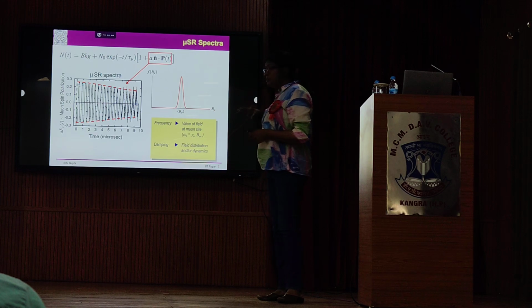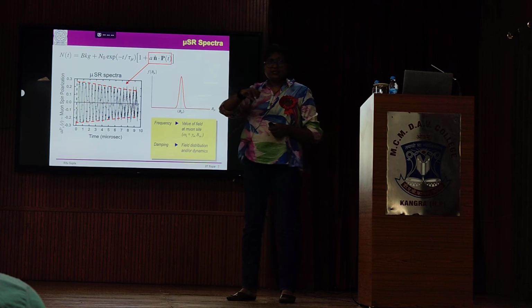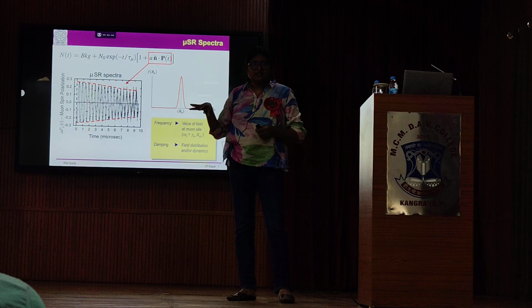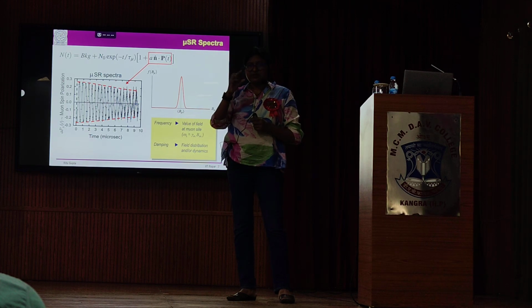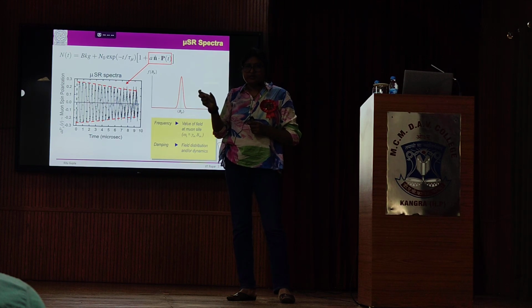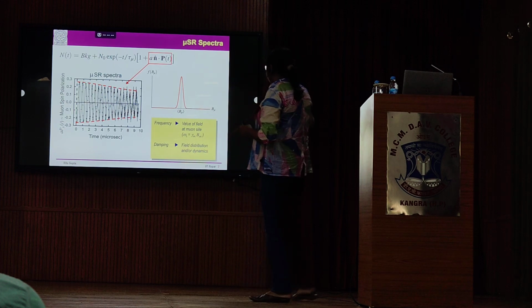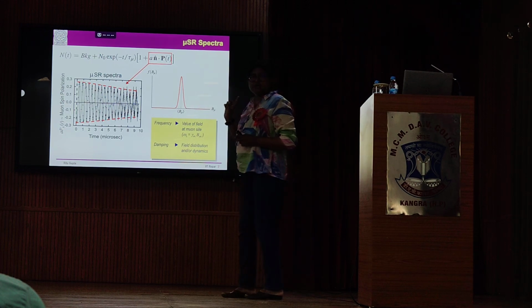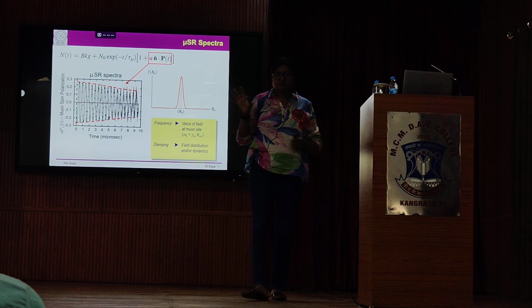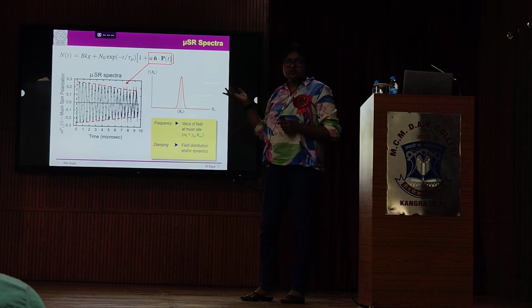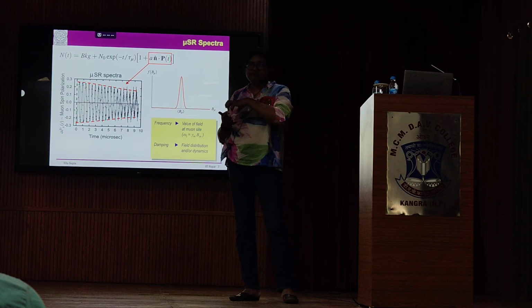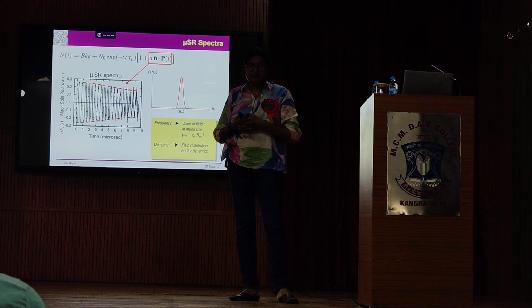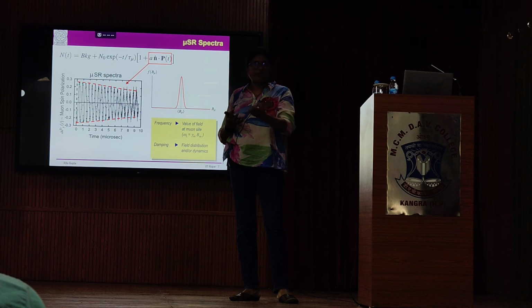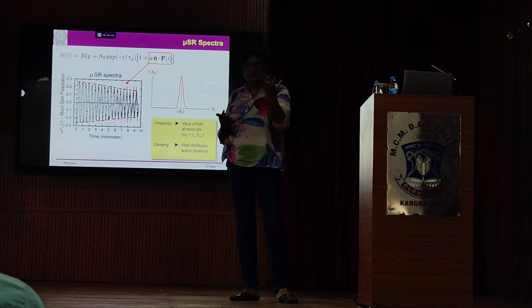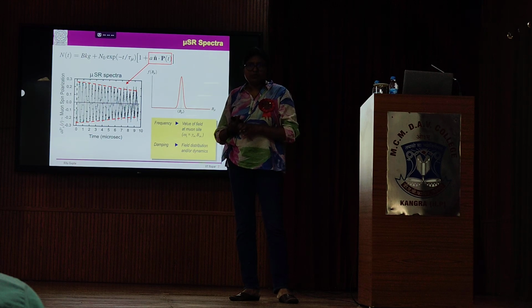Okay, but if the field inside that material is inhomogeneous, you will see not a single peak but a broadening in that peak. Okay, so that broadening is basically giving you the field distribution inside, for example, a superconductor. In a superconductor, the field distribution is not very uniform because at some places you have magnetic field, at some places you have normal matter.